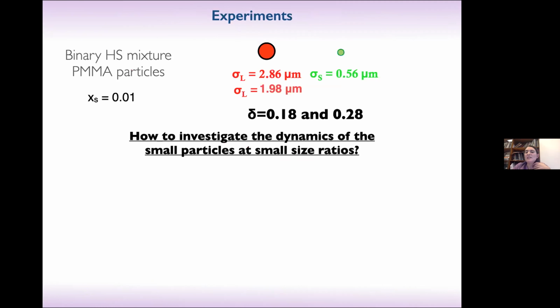We were interested in this because our collaborators in Düsseldorf studied this system experimentally, taking two hard spheres, one much smaller than the other, and they worked at two size ratios, roughly 0.2 and roughly 0.3. And the breakthrough of this work was the following: even though these small particles are very small and cannot be resolved by confocal microscopy, their 3D trajectories cannot be resolved, and so you cannot calculate their mean-square displacement, for example, the dynamics, with just standard confocal microscopy.